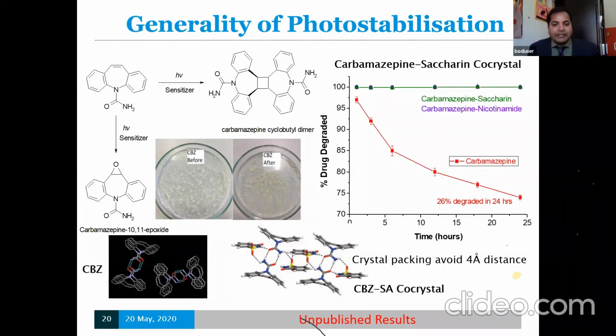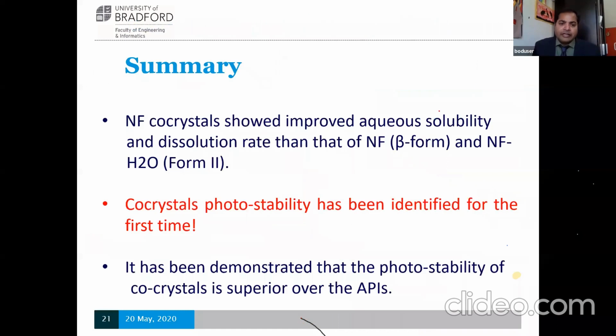So with that in mind, we explored the photostabilization studies, and we found that both carbamazepine saccharin and carbamazepine nicotinamide have offered photostabilization. This study was the first of its kind when we published this photostabilization using co-crystallization technology. In recent times, there were a few studies from Chinese groups. They have looked into vitamin D and some other cases also, on what photostabilization could be offered if you prepare co-crystals.